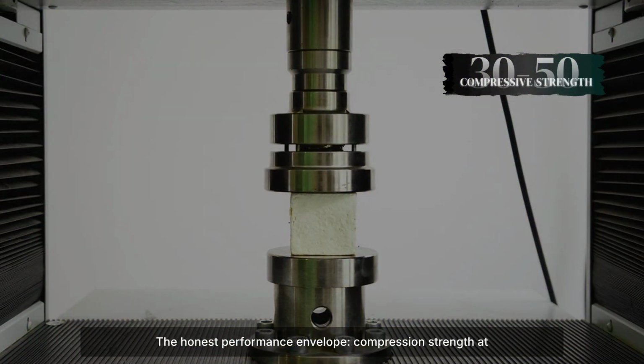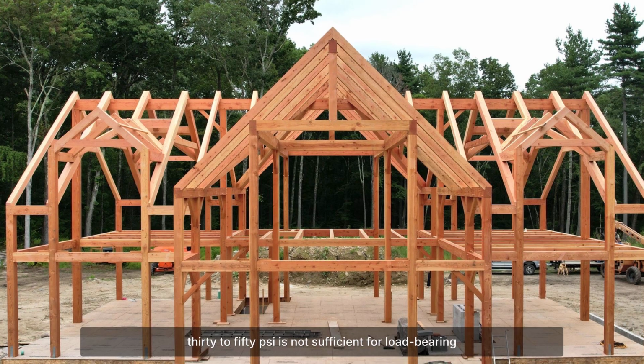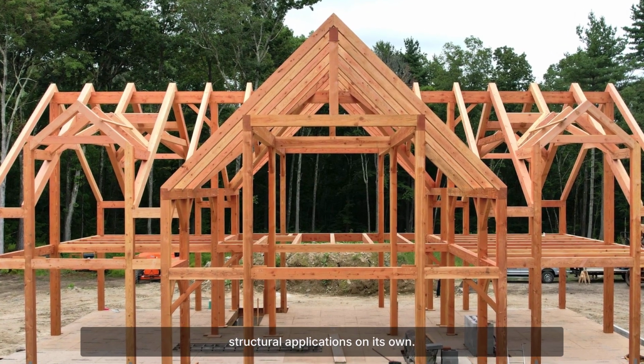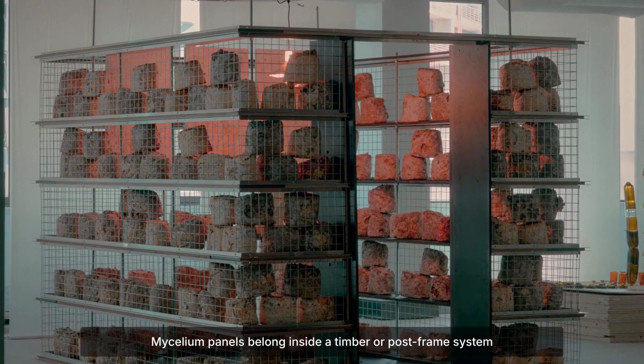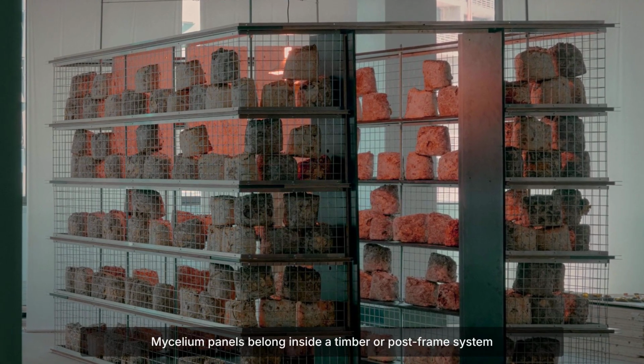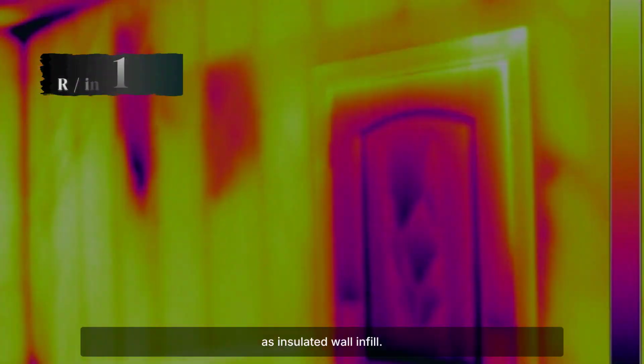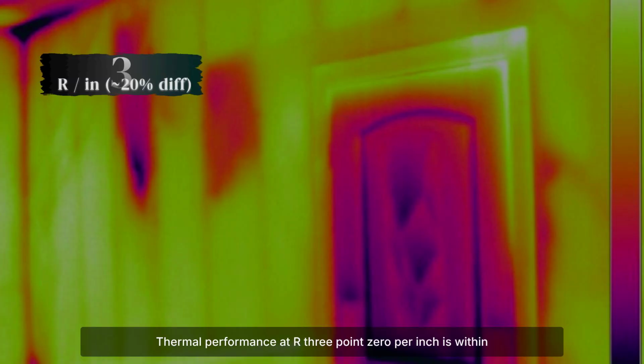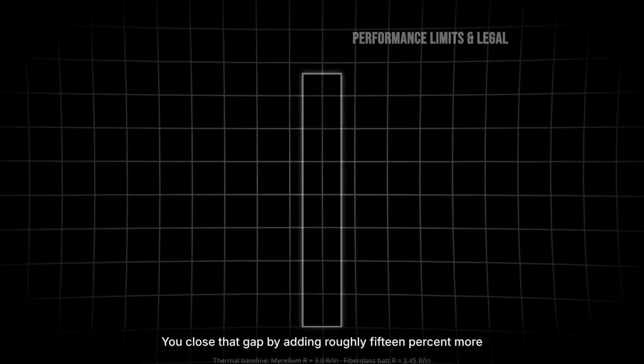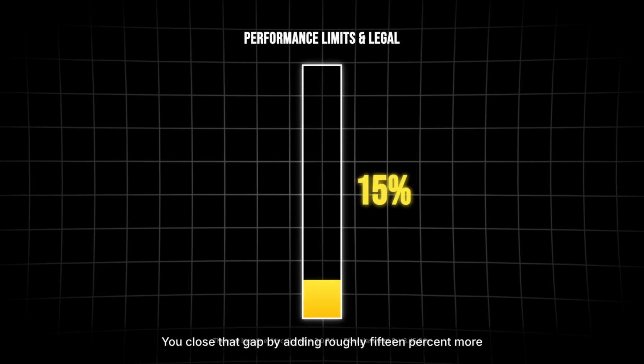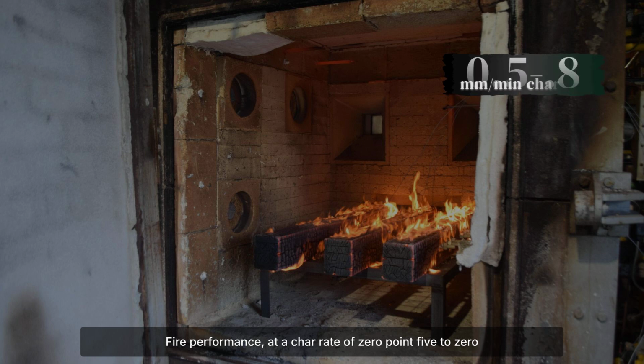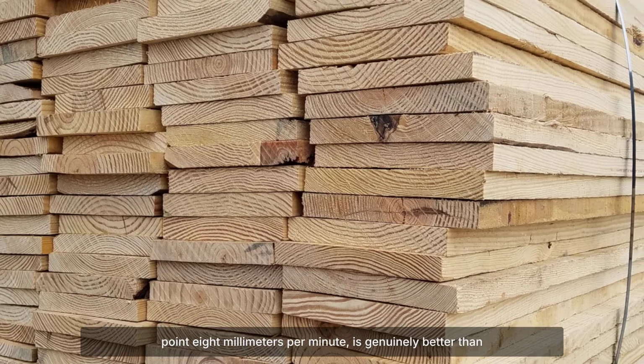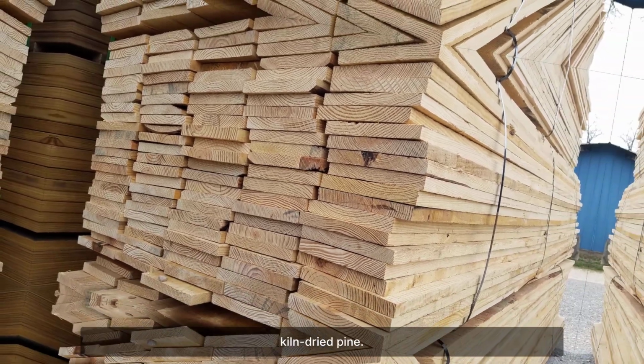The honest performance envelope. Compression strength at 30 to 50 psi is not sufficient for load-bearing structural applications on its own. Mycelium panels belong inside a timber or post-frame system as insulated wall infill. Thermal performance at R-3.0 per inch is within 20% of fiberglass batt. You close that gap by adding roughly 15% more thickness. Fire performance at a char rate of 0.5 to 0.8 millimeters per minute is genuinely better than kiln-dried pine.